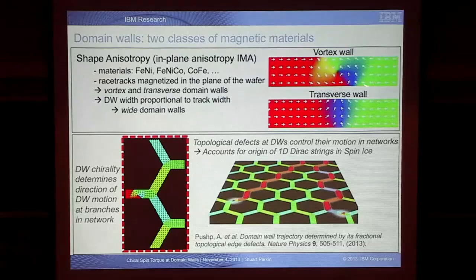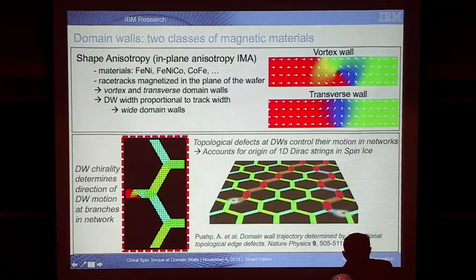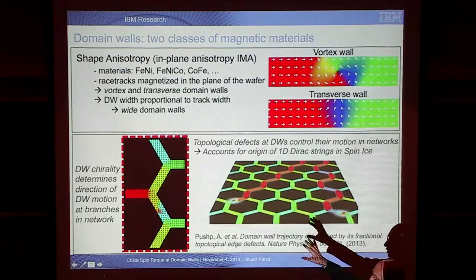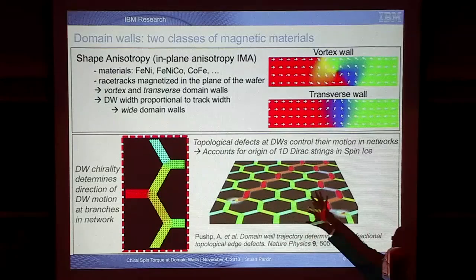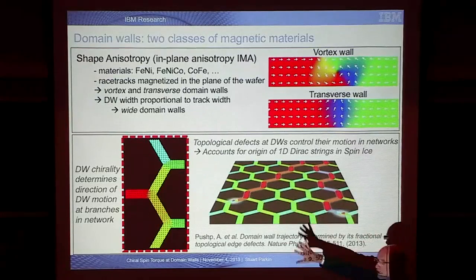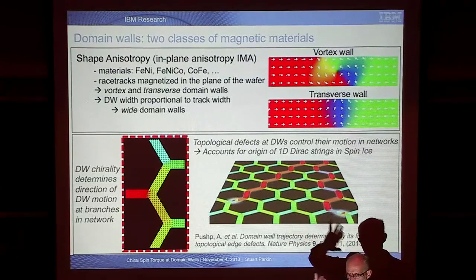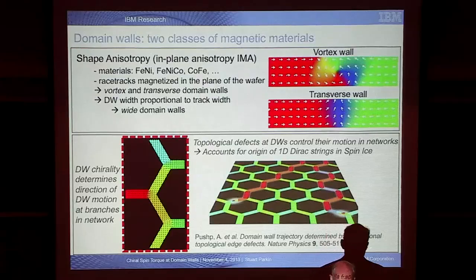They have clockwise and anti-clockwise so-called vortex and transverse walls. I don't have time to discuss this, but it turns out that we can build interesting devices by controlling the chirality, and in networks of magnetic wires, the chirality of the domain walls will determine how they flow through the network. So we think this is pretty interesting for creating new types of logic devices.